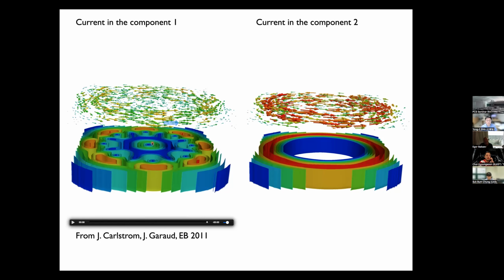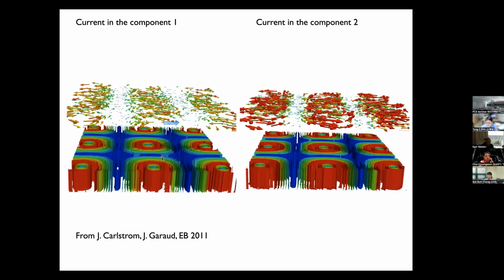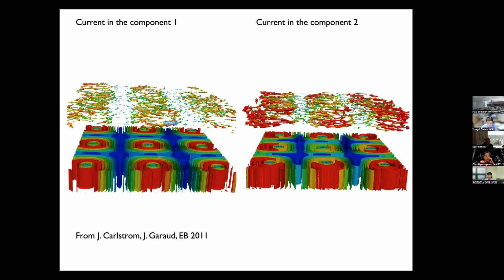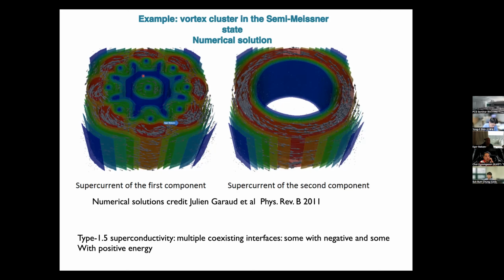So this question of whether the interface energy is positive or negative is only a consequence of assuming that the interface is translationally invariant along the interfaces. Translational invariance can be replaced by 1D. And in general, this example shows that you generally have infinitely many complicated interfaces. Let's say inside the clusters, the interfaces have negative energy. It wants to create as much phase separation and vortices as possible, but the interface of the cluster itself has positive energy.